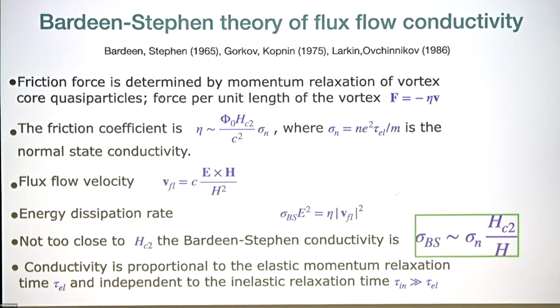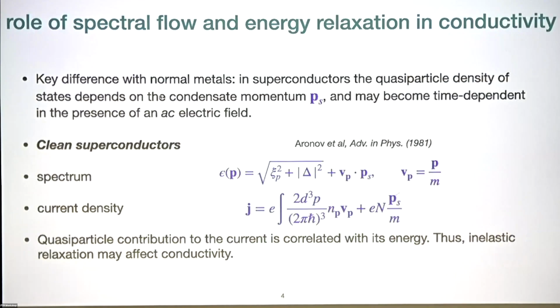What's important is that the flux flow conductivity in the Bardeen-Stephen theory is proportional to the short elastic relaxation time, and the long inelastic relaxation time does not enter at all. And so, continuing Boris' talk, I will discuss under what conditions the long inelastic relaxation time can appear in the conductivity of these type 2 superconductors in the mixed state.